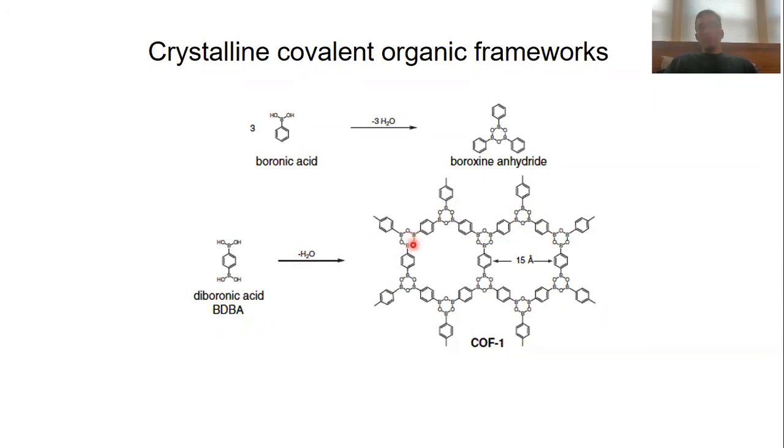So even though the boron-oxygen bonds are not dative bonds in the classical sense, like it is the case in metal organic frameworks, we can still labilize the boron-oxygen bond through hydrolysis. You need to imagine that there is a nucleophilic attack of that water on that boron here, which is electron deficient, and that can then cleave a boron-oxygen bond.